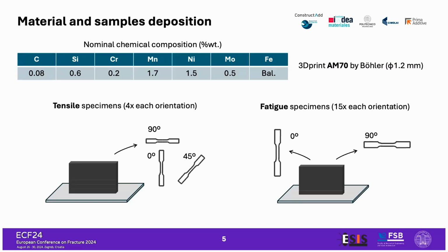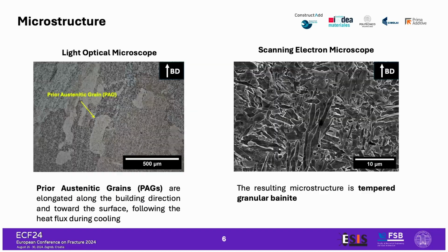For the mechanical tests, we performed two different depositions and we extracted tensile and fatigue specimens with different orientations, as you can see in the slide. This was also to be able to assess possible anisotropy, which is typical for additive manufacturing technologies.